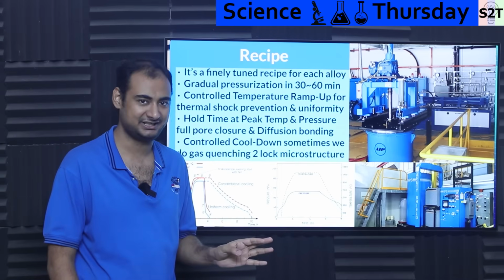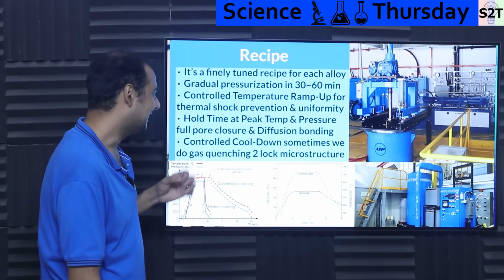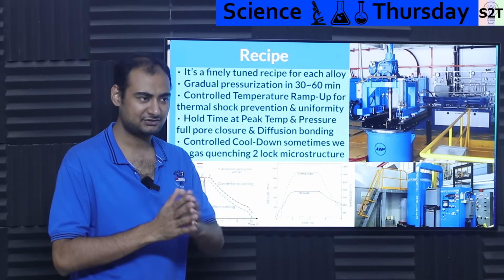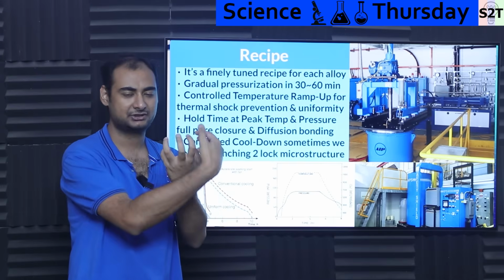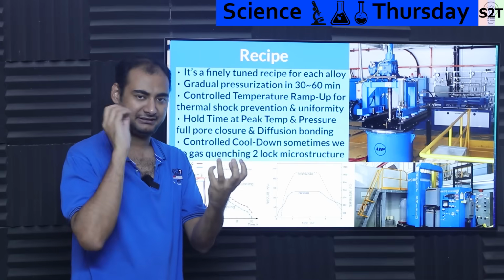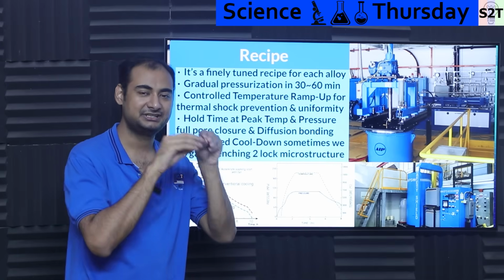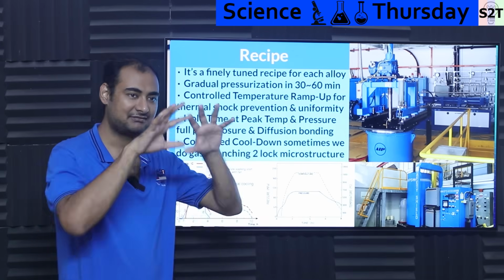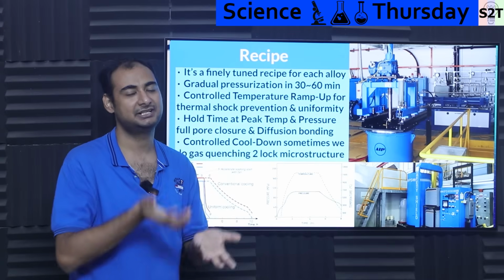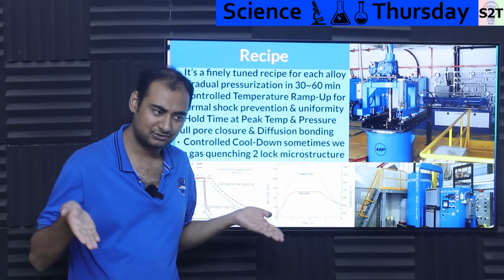Does not matter which alloy it is. So for that reason, we have to gradually raise it, because you have to understand, even if you have an object and a very high pressure ecosystem around it, if you heat it up very quickly, it will take time to heat up from the inside. So you will have the outside hot and the inside cold, and that will create stress. So for that reason, you want to thermal soak it.